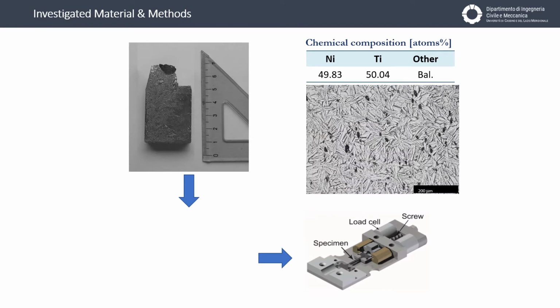The product of the casting is the ingot. It's a very short ingot. The height is around 5 centimeters, and the material has been characterized both in terms of the chemical composition. You can see that the quantity of the nickel and titanium in atoms is quite similar, and in terms of microstructure you can see the magnification. This is around 500 times magnification.